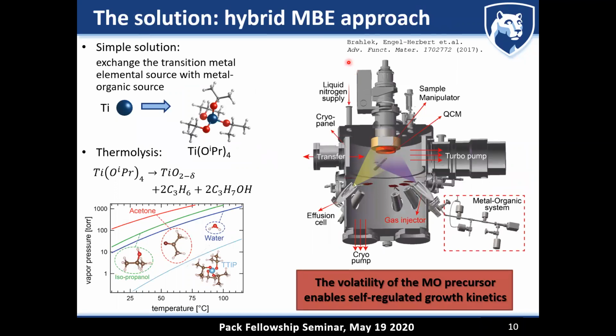We published this 10 years after making use of a very simple solution. We call this hybrid molecular beam epitaxy. And the idea here is that we're going to take the actual troublemaker in the growth of molecular beam epitaxy of complex oxide, in this case, the titanium. We're going to take this troublemaker titanium and replace it with a metal organic molecule.